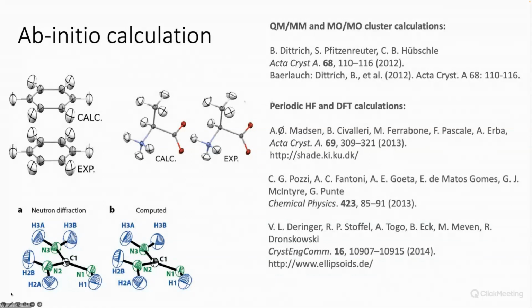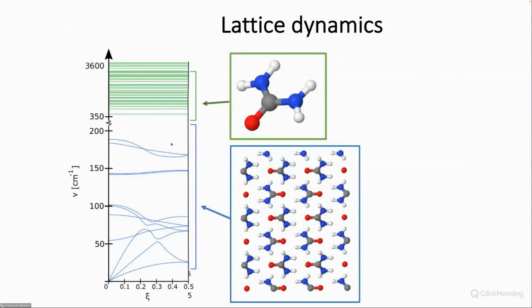So we have calculated, and many others have done the same. You can see a list of references to the right here. You can calculate based on periodic DFT calculations, or you can also use molecular dynamics simulations. You can calculate the thermal ellipsoids, and you can see the difference here between the calculated and experimental ellipsoids coming from neutron diffraction is actually not that large. It's a fairly accurate approach. So with that sort of tool in hand, we can come quite a way.